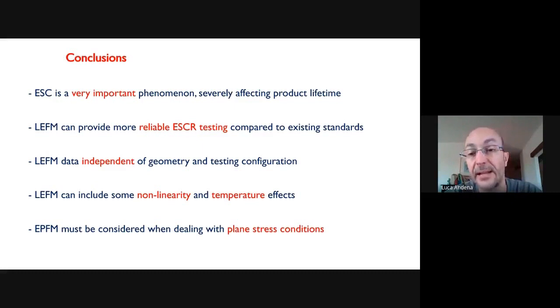Of course, this is all valid as long as you are in plane strain conditions, which are the typical conditions you use for testing. However, on some materials, including, for example, polyethylene, when you have plane stress conditions, such as on thin products, then probably the amount of plastic deformation you develop will be much higher. And so for stress cracking, as for environmental stress cracking, you will need to rely on something else like elastoplastic fracture mechanics, which of course is more complicated, but in those cases can give you more accurate results.